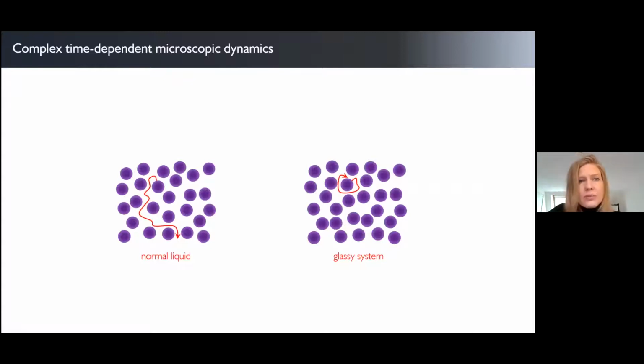Now, zooming in on the dynamics a bit more, I already mentioned the viscosity, which is, of course, a macroscopic material property, but you can also look at simply the motion of individual particles. And then the most obvious difference between a liquid and a glassy system is that in a liquid, particles can move around relatively easily, while in a glass, the particles tend to stay very close to some equilibrium position, and in the solid phase, they will only vibrate a bit around that equilibrium position.